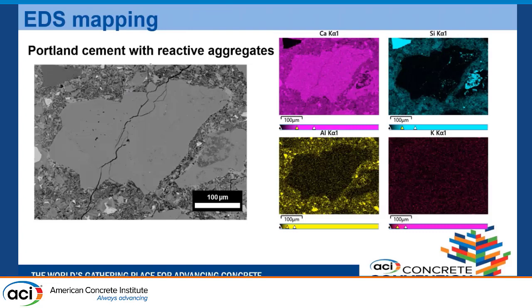This is an image of what I'm doing. Currently, I'm using EDS and a mapping technique to get the composition, because I want to find ASR gel and get more information on the chemical composition of the gel itself. What you see here is Portland cement with reactive aggregates. Let's start with calcium. What we expect is that we have Spratt siliceous limestone, so we do have traces of calcium there. It's pink, and all the paste also has calcium.